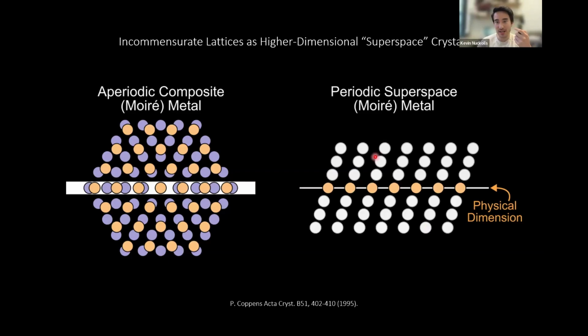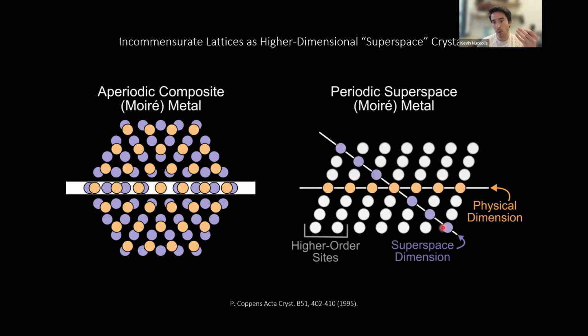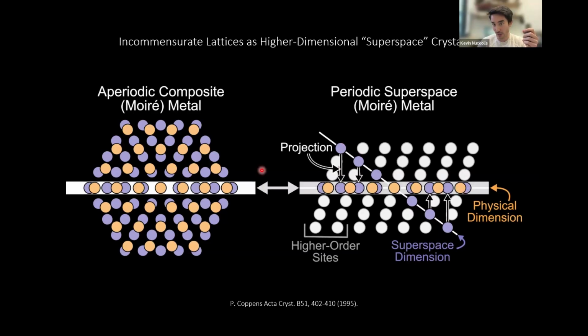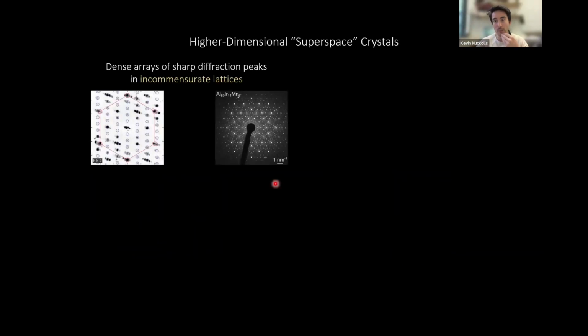To understand this construction, we have this physical dimension, and I've elevated the structure into one higher superspace dimension. And then if we project from the superspace dimension back into the physical dimension, we recover the incommensurate lattice. So this seems like a party trick, but actually I assure you that it works for all incommensurate lattices seen in nature. And it's the thing that endows incommensurate lattices with long-range order, with sharp diffraction peaks. And so looking at this problem, we think that this is very related to our current problem in our paper.